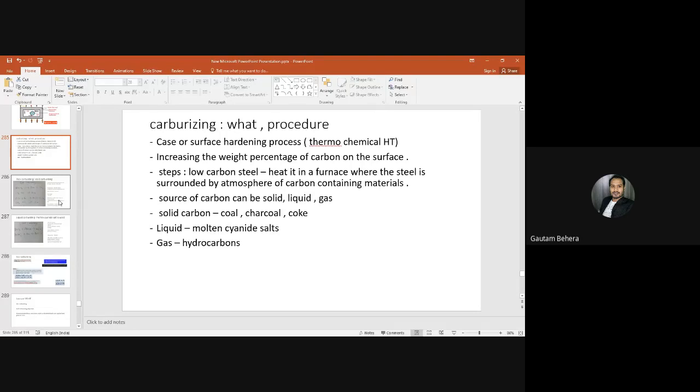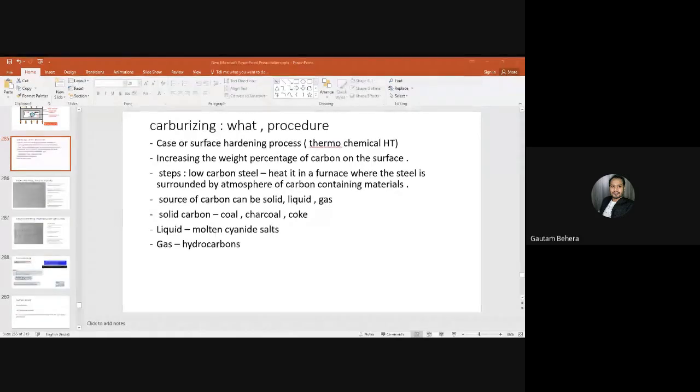Network of carbides may form. You understand? If the concentration of carbon is so high, near 1 weight percent, sometimes a network of carbides forms. And are network carbides good or bad for the steel properties? Bad. Yes. Why are they bad? Crack propagation will be easier. Why? Because networks of carbides are there. Carbides are basically brittle in nature. If a crack initiates, it will find an easy path for its propagation. So that may be another reason for giving post carburizing heat treatment.